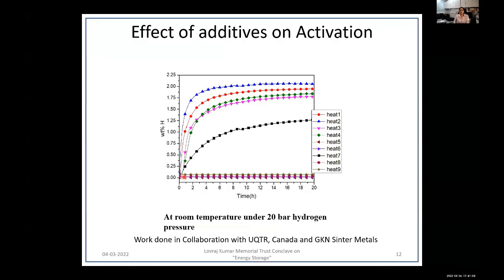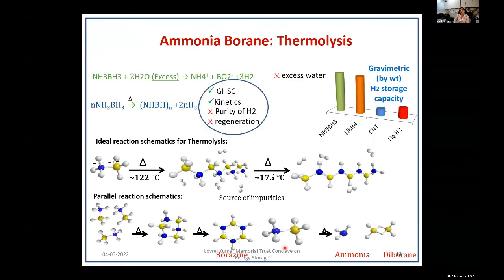So if it is pristine, there is no activation taking place in hours. But as we dope it with different elements, we can see that the activation gets much faster. Earlier you had to heat at 400 or 600 degrees for 12 hours. Now we can do the activation at room temperature and at 20 bar. There is an industrial partner and a Canadian university involved in this work. So these were some examples of one class of hydrides, which are metal hydrides.